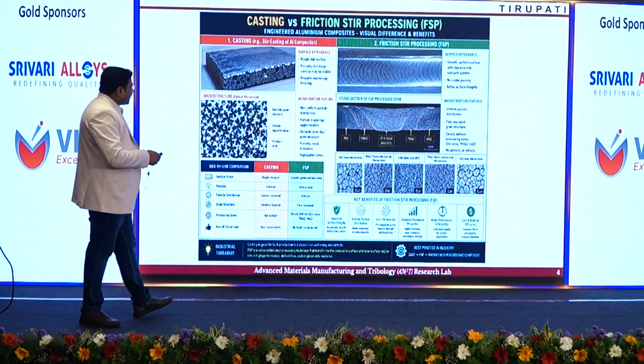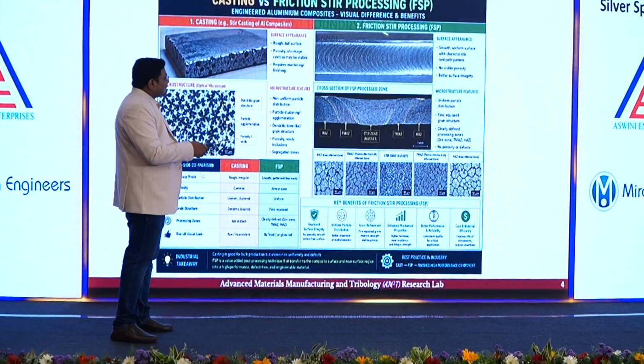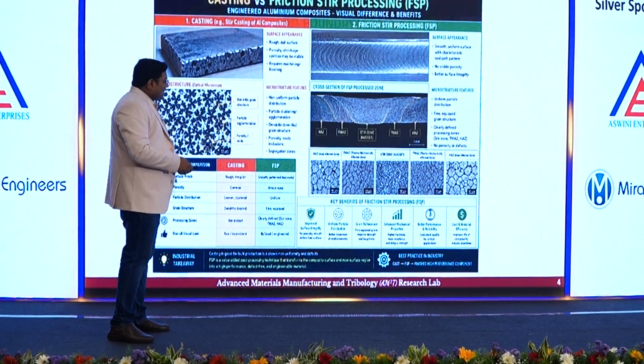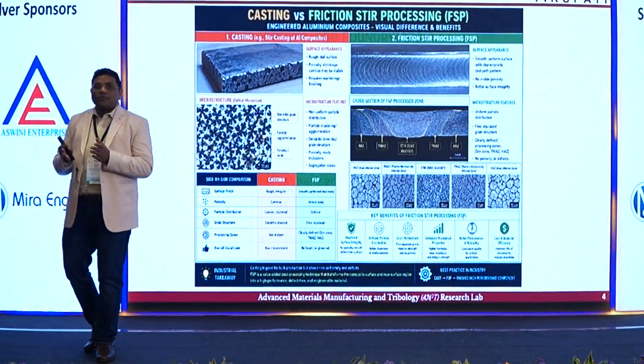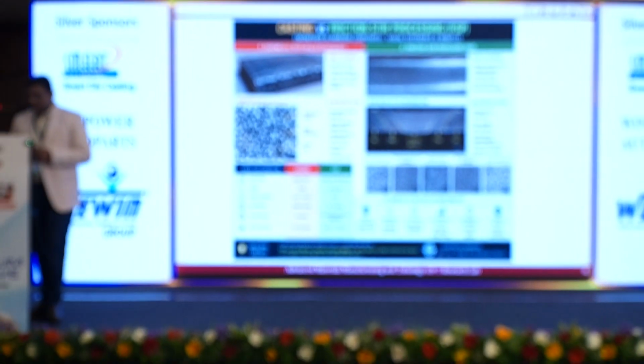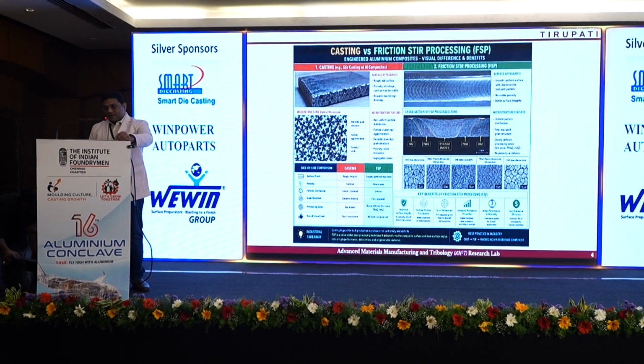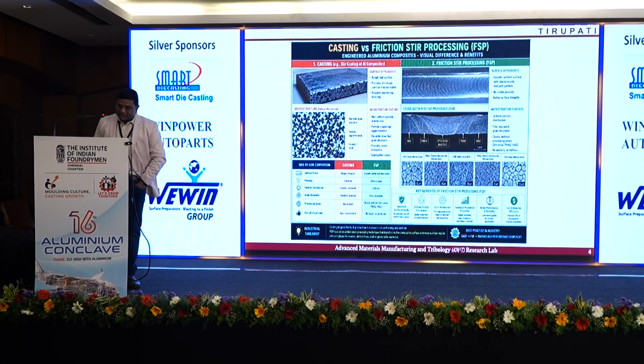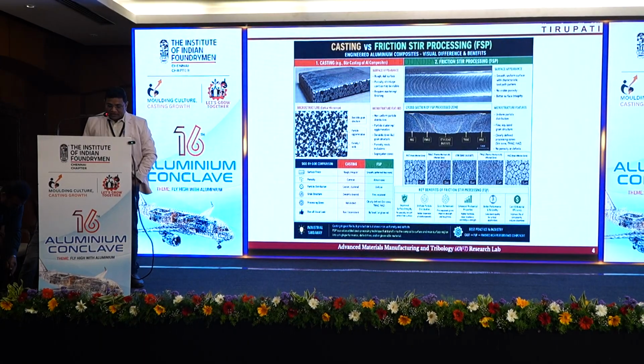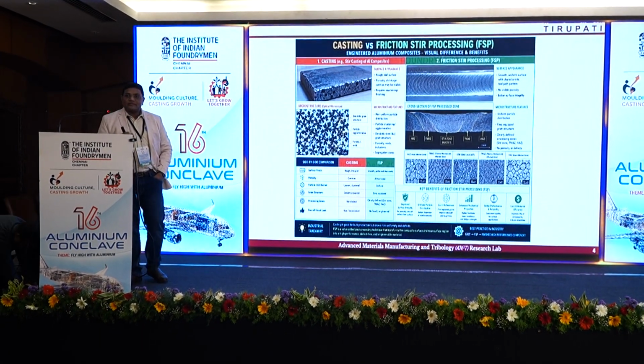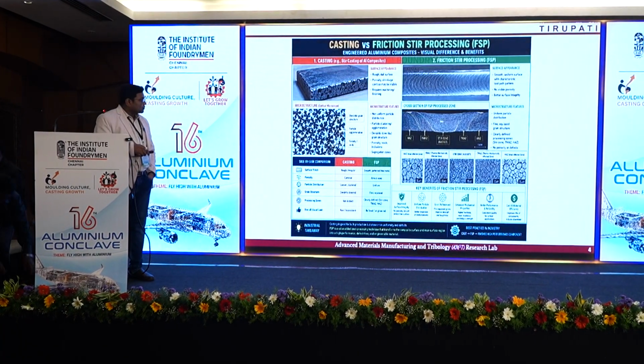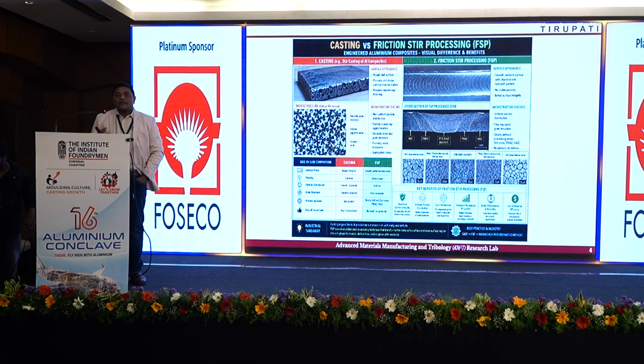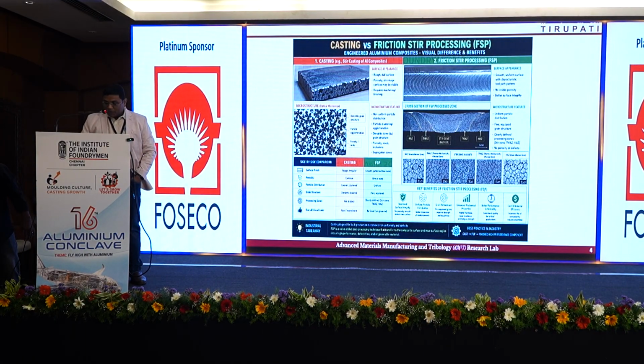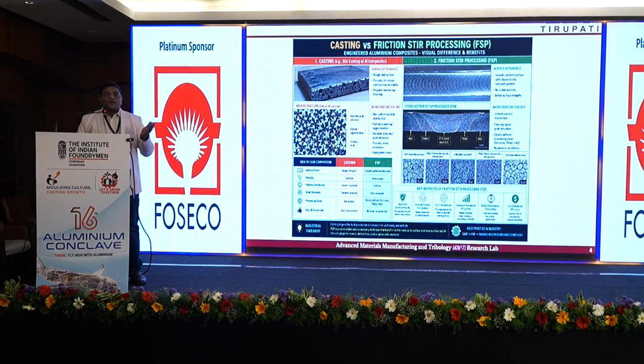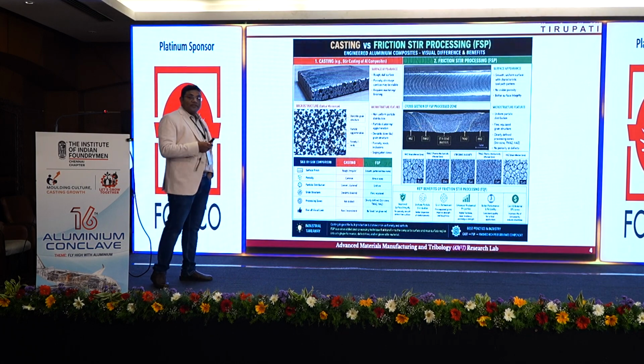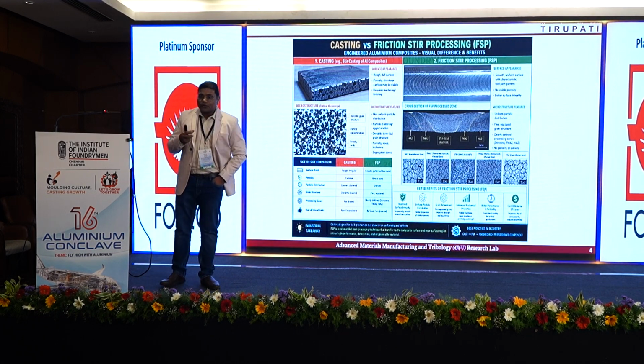So in casting you have a lot of defects, and this is friction stir processing where you are refining the microstructure, and you can see you are going from various microns to the submicron or sometimes the nano scale. So in casting you have a very rough surface, and also a lot of porosities, voids, and defects, and the grains are mostly dendritic grains in most castings. But when you are doing this process, you are refining the dendritic grains, and it is becoming more refined, which will improve the properties of the component. So that is the advantage of integrating this friction stir engineering into your casting.